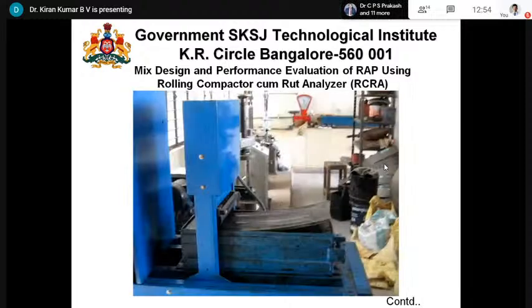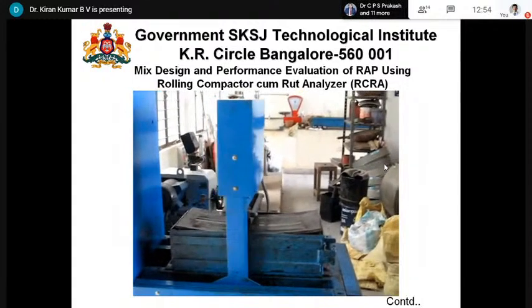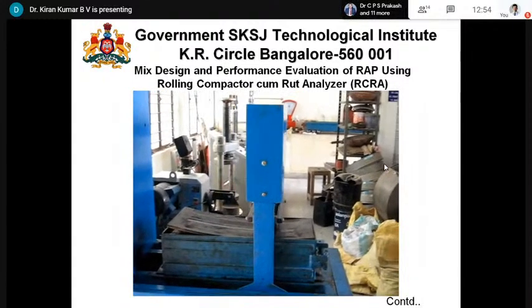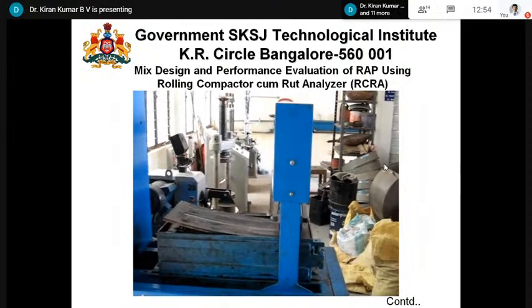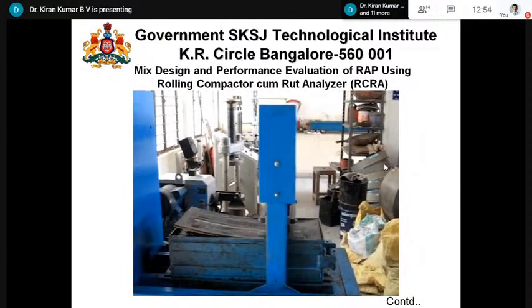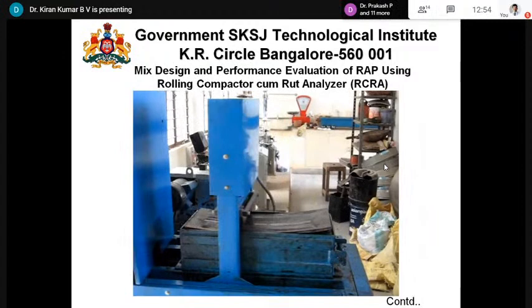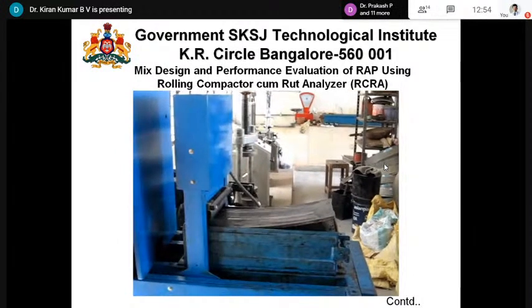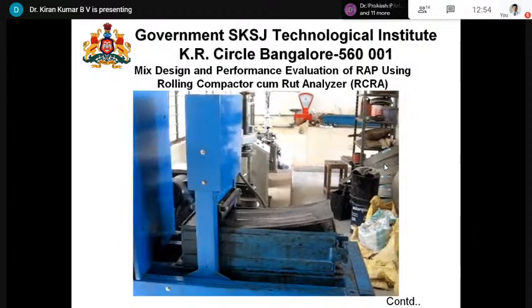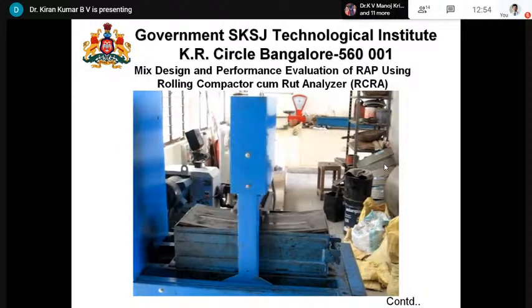It is a similar procedure and quantity of bitumen, the optimum binder bitumen content, that needs to be analyzed. We have analyzed it. This video shows you how the slabs are constructed using this roller compactor. It is a recycled material that we have used. There are different compaction levels you can do. We have done it for the surface course and we have found out the optimum binder content.